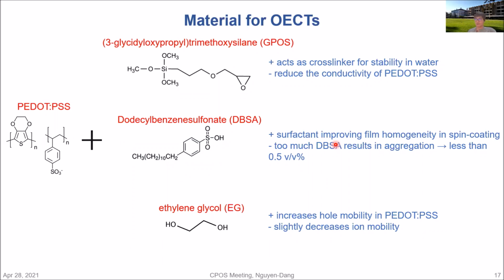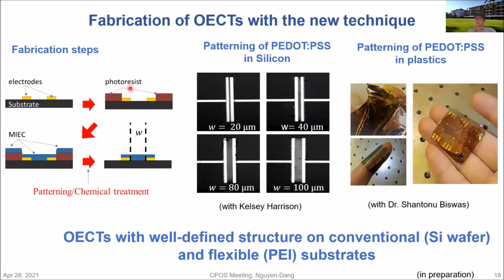I chose several dopants, like ethylene glycol, to enhance the conductivity of the PEDOT:PSS. I also chose DBSA in order to improve the film formation of the PEDOT:PSS and increase the viscosity. And I added a cross-linker, GOPS, in order to stabilize the PEDOT:PSS in aqueous solution. So with these materials, I implemented the techniques.